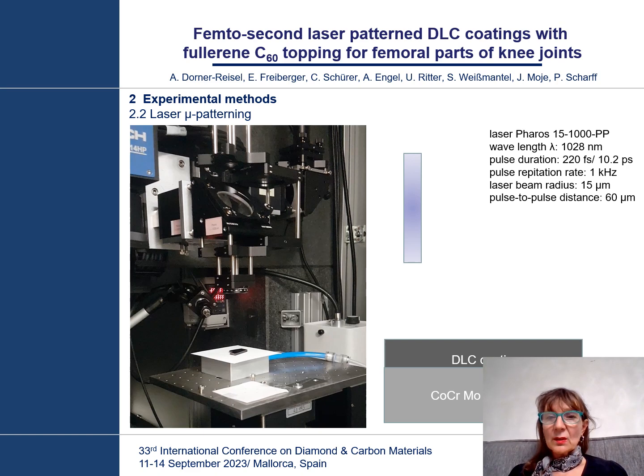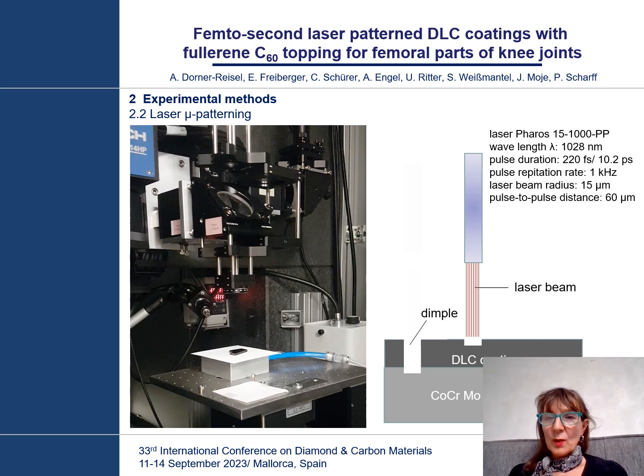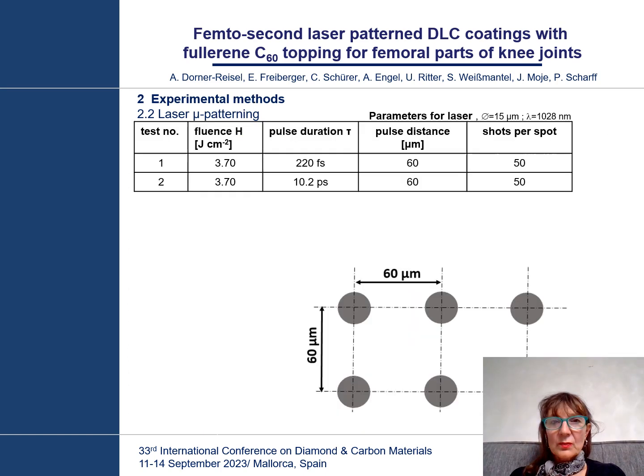Following DLC deposition, a laser patterning process was performed, and two different pulse durations were applied. On the one hand 220 femtoseconds, and on the other hand 10.2 picoseconds. The distance between the single laser shots in transverse and lengthwise direction was 60 microns, and each dimple was formed by 50 shots per spot.